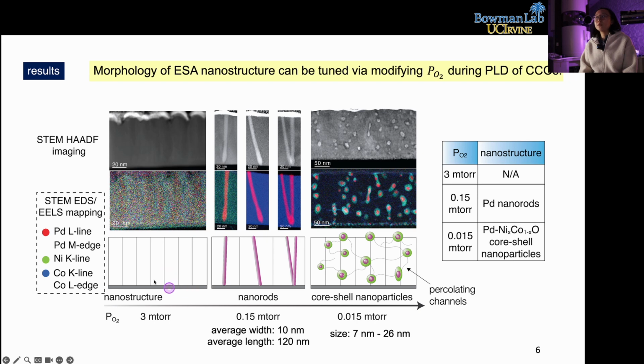At 3 millitorr, we can see no nanostructure formed inside the films. But when the pressure drops to 0.15 millitorr, the palladium nanorods get exsolved and grow through the thin film from the bottom to the top. And when the oxygen partial pressure drops by 10 times to 0.015 millitorr, we can see the exsolved nanoparticles distributed inside the thin film and also on the top surface.